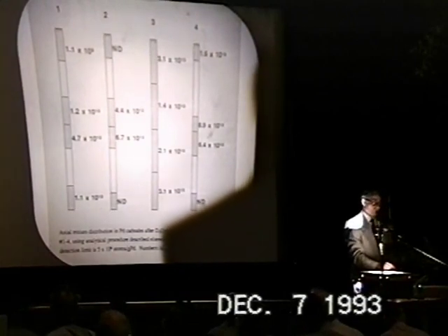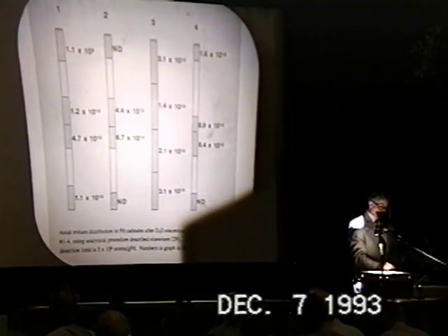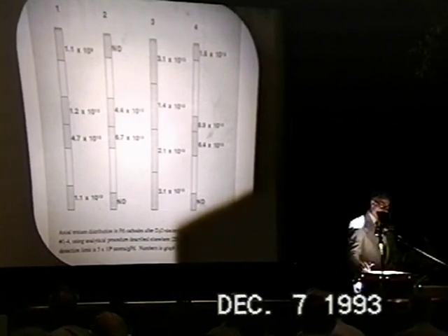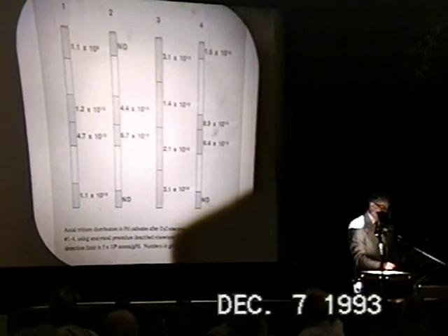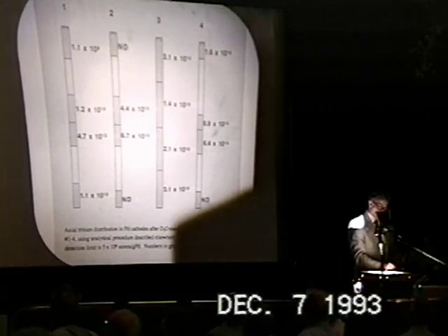After any of these 4 experiments with electrolysis, we are left in a charged state, meaning the tritium was to a large extent still contained in the palladium electrodes. They were then cut into various pieces, namely the shaded pieces are the ones that were cut from the electrodes and analyzed for tritium. And this gave us the possibility to come out with a distribution in some form at least, in these palladium electrodes.